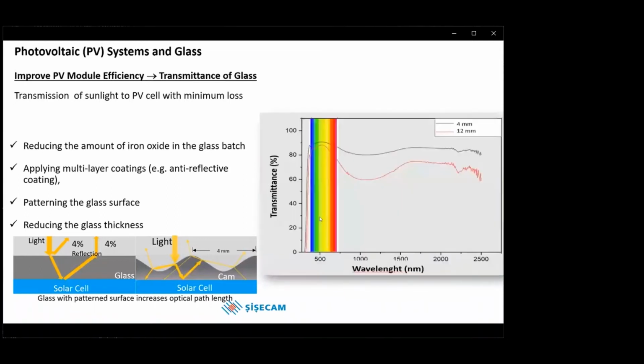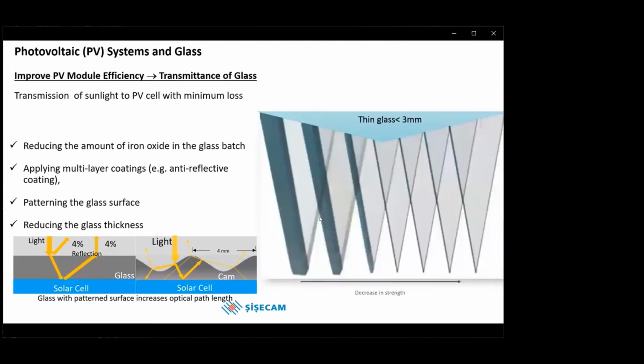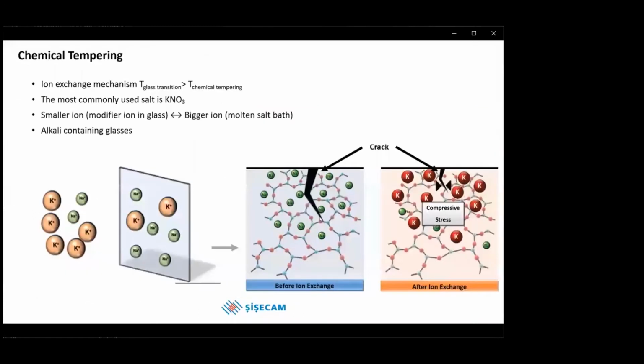Reducing the glass thickness: thinned glass used in photovoltaic modules has become one of the highlights of the glass industry. It has been determined by previous studies that the thinner the glass, the higher the transmittance of the glass. However, as the glass thickness decreases, the strength values also decrease. At this point, the chemical tempering process is used to increase the strength of thinned glass.